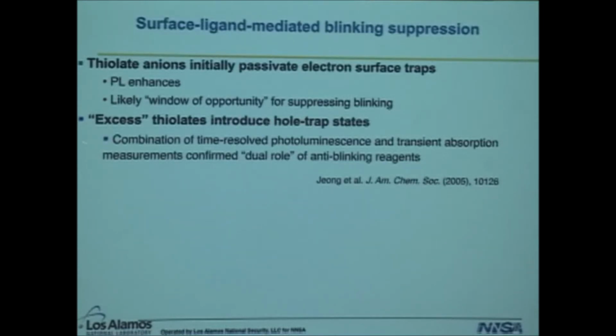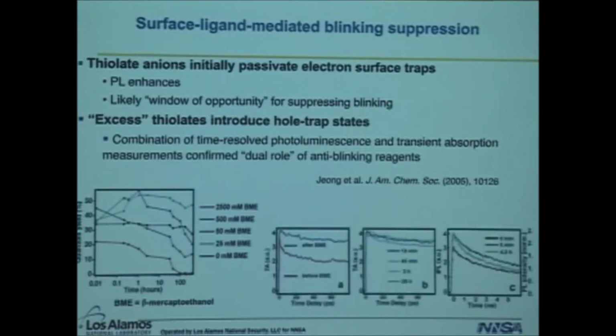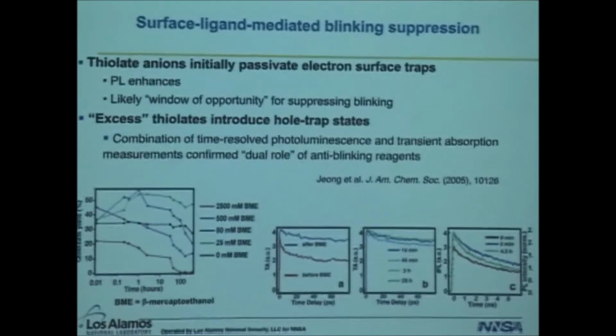And we used a combination of time-resolved PL and transient absorption methodologies to confirm that these so-called anti-blinking reagents actually serve two roles. One, initially to passivate traps, and two, to actually introduce traps. And we published this several years ago in JACS. In other words, it's very difficult to apply these organic compounds in just the right amount and at just the right time, and to hold it at the right pH and so on. A number of conditions were affecting the results that you obtained.